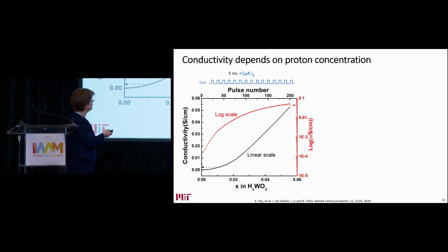And again, if you look at tungsten oxide, it's a very sensitive material to hydrogen in the low concentration regime. So up to a few percent, you can get more than 2 orders of magnitude increase in conductivity, and that's more than sufficient for the purpose of hardware DNNs.